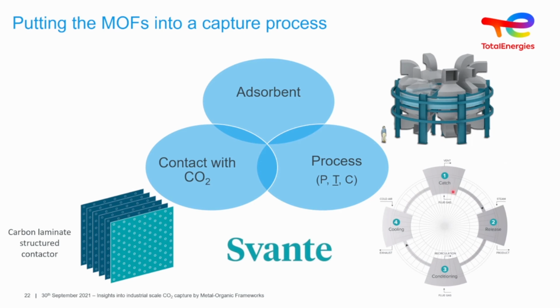What is of interest here? Why can they go so fast? Quite simply because they have this contactor, which is a laminated contactor, and the CO2 comes through these laminates. And they make sure that the laminates are just the right size so that there's a full contact of the flue gas as they go through this bed, which is about 1 meter high, 1.2 meter high. And they use an adsorbent material, which is on these laminates.